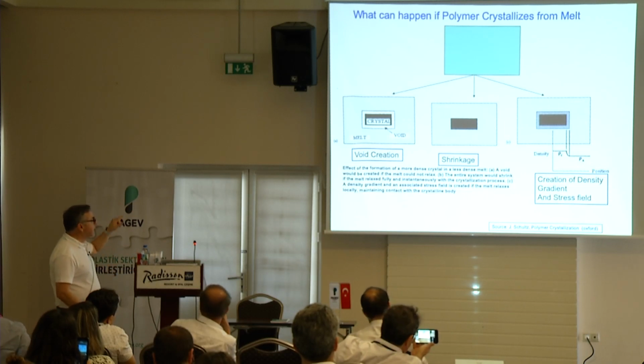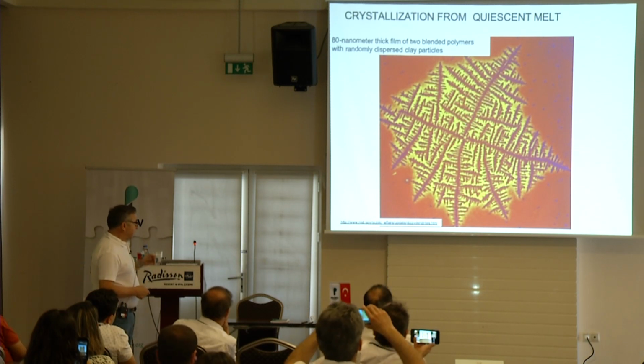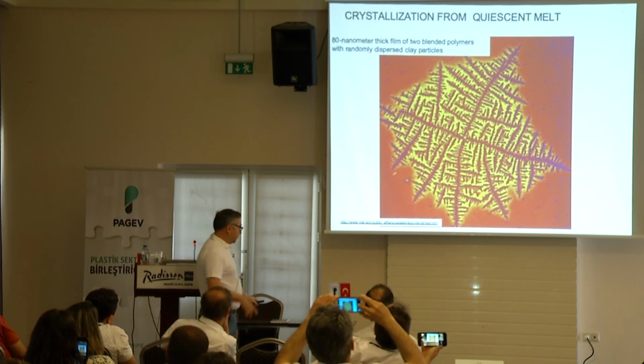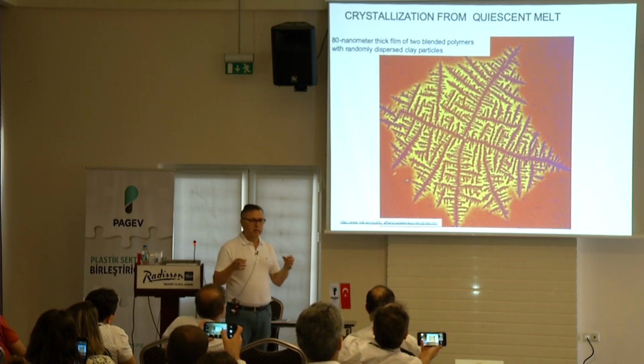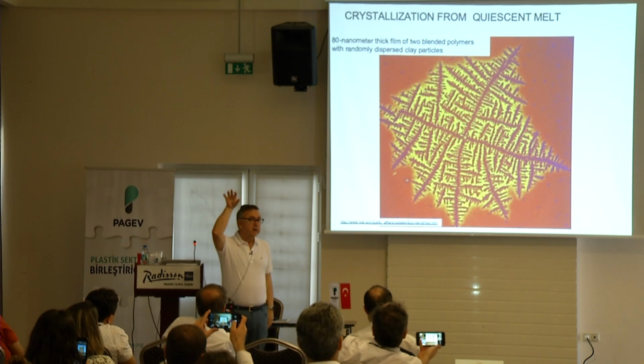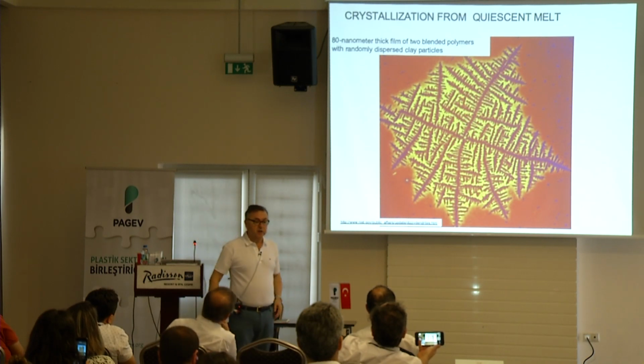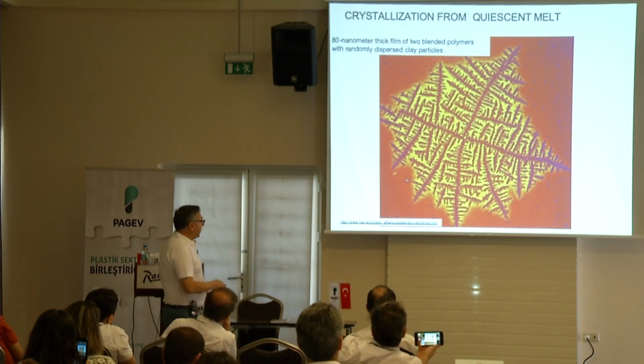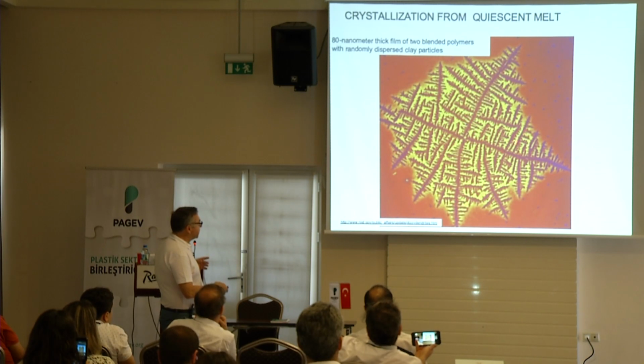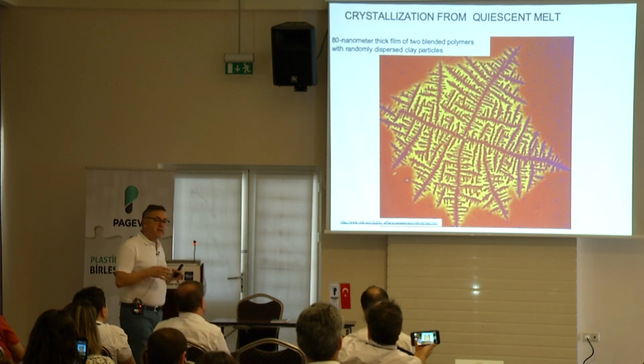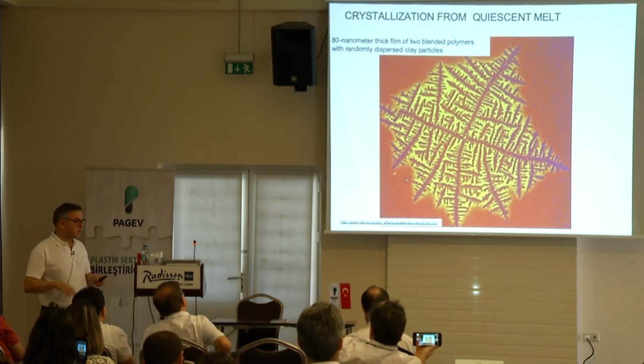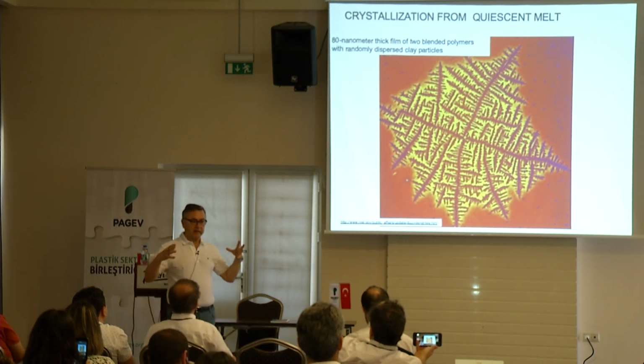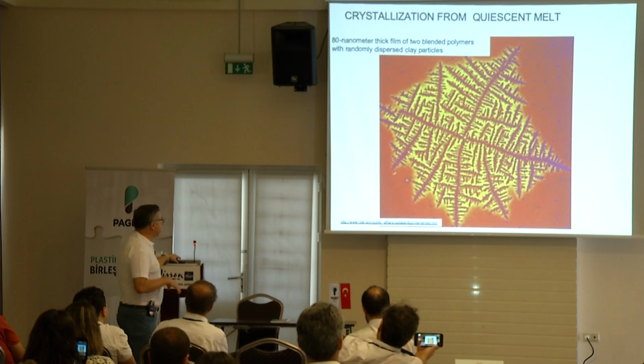Important. So that's one of the things on polymer crystallization. So, quiescent melt. The word quiescent means undisturbed. You're not doing anything. You just simply take molten material and gradually cool it down. And this is the kind of structure that you would get in two dimensions, a dendritic-like structure, okay? This happens to be a blended polymer so that these dendritic structures are much more apparent. You can see the internal structures of these materials. So it's not uniform. The crystallization process is not necessarily uniform. It's not what's called, let me repeat that, it's not volume filling. So if you watch it, I'm going to show you a video.